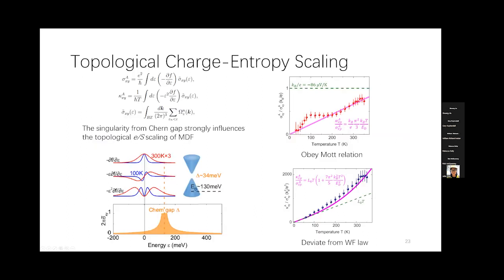So for the anomalous effect, basically the formula is similar. The only difference is that we replace the sum of the Berry curvature over the whole Brillouin zone with the transport distribution function. So we multiply by the derivative of the Fermi distribution function and this sigma xy, and we have the finite-temperature anomalous Hall coefficients, including the anomalous Hall effect, anomalous Nernst effect, and also the thermal Hall effect. So in this plot, I plot the window function at 100 Kelvin and 300 Kelvin for these 2 different anomalous effects. I also plot the Berry curvature distribution for the massive Dirac fermion.